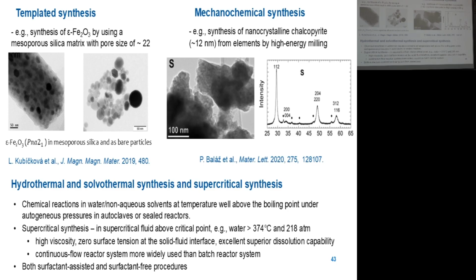and we purified it and obtained single phase pure epsilon iron oxide, which is really a fascinating material because it has huge coercivity. This is the absolute opposite of superparamagnetic nanoparticles. These particles are extremely blocked. They have a coercivity of around 2 Tesla. But still, you can use them in medical applications, for example, as a contrast agent for magnetic resonance imaging, but I guess they are not very useful for magnetic particle imaging. So this is just a special example.